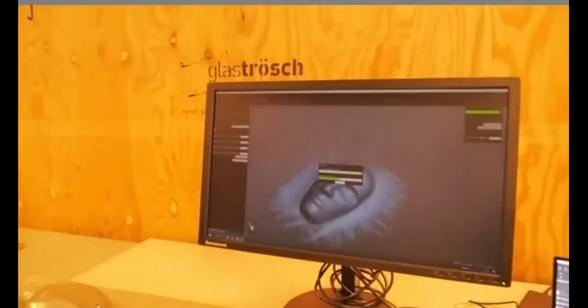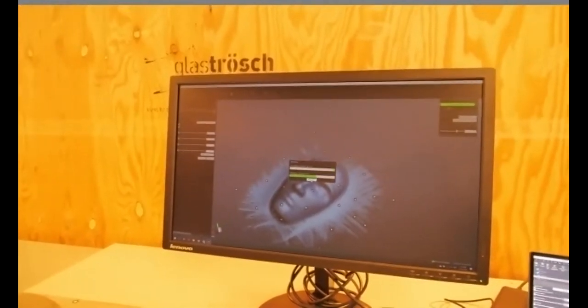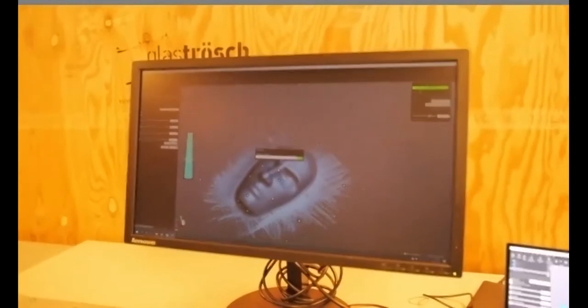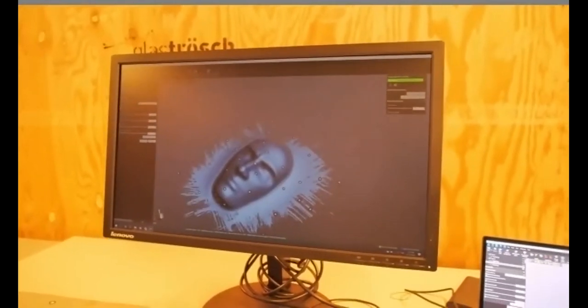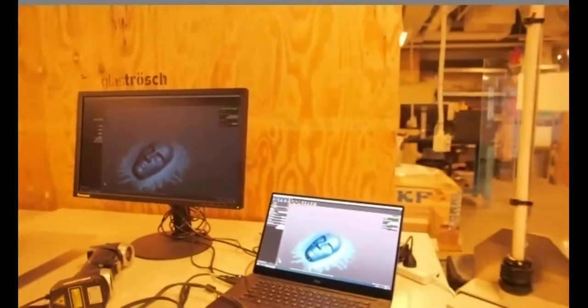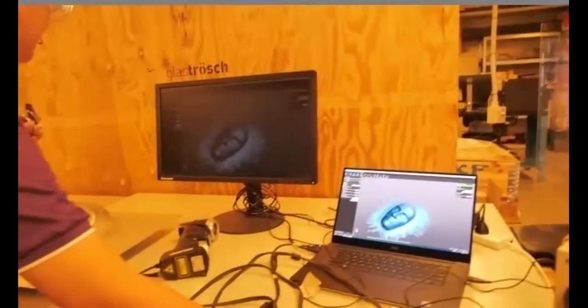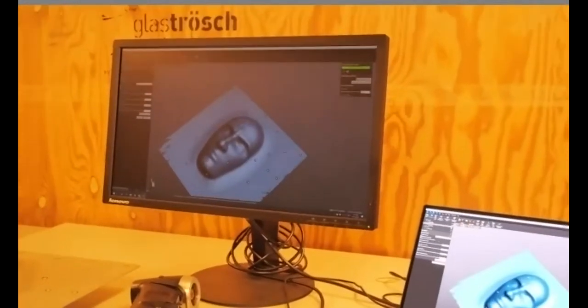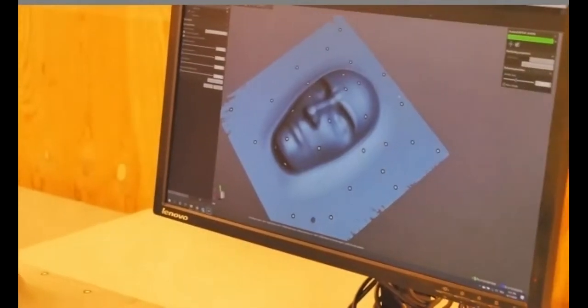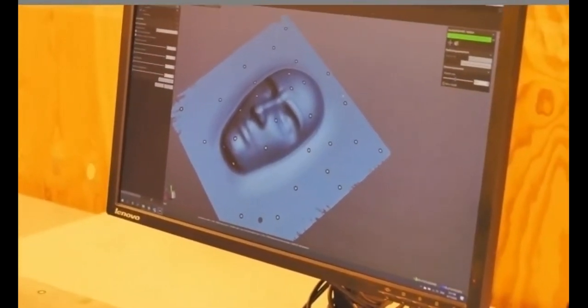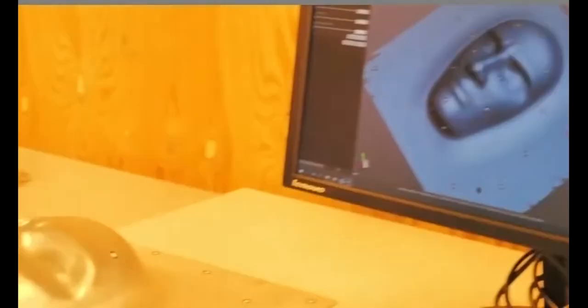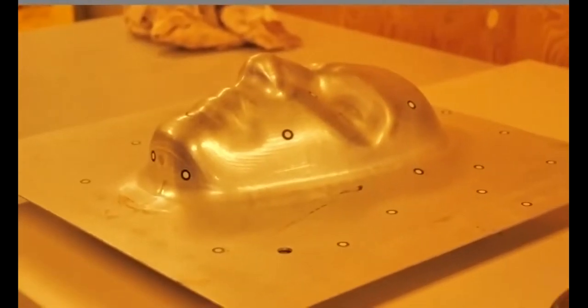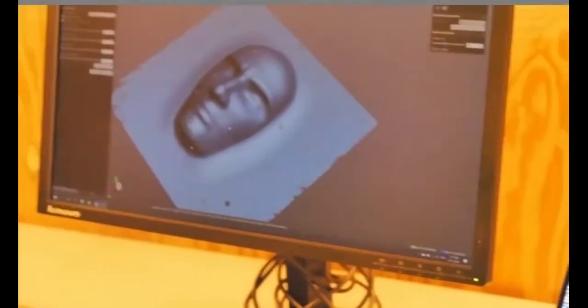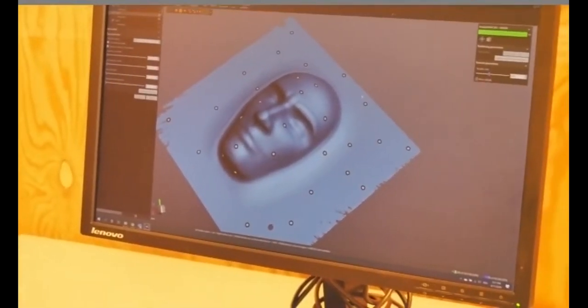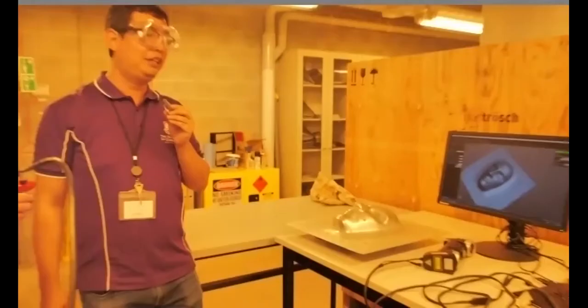and also we use this scanner in a few different scenarios. Firstly, obviously we're trying to check the accuracy of our forming. We also use this scan as a feedback control, which we actually divide our forming into a few different steps. And so this is a full scan, you can see. We subdivide our forming into a few different steps. And once we've done one step, we do a scan and we have developed a control algorithm to actually change the forming process of the next step, trying to compensate all those errors. So the purpose of that control is we can get the accurate forming in just one go. We don't have to use try and error.